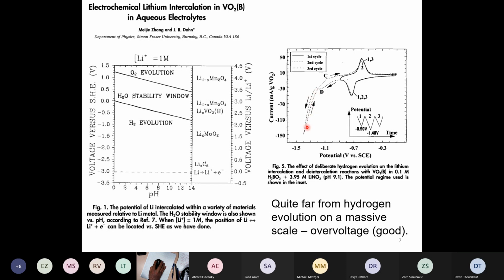So this gigantic current spike that you see happening at low voltage is the hydrogen evolution. So it turns out that at pH 9, which would be about here, there was quite a kinetic hindrance to the hydrogen evolution reaction, a big overvoltage associated with it, as you can see, maybe about 0.4 volts or so based on the scale here. And this is common for certain electrodes in aqueous solution.